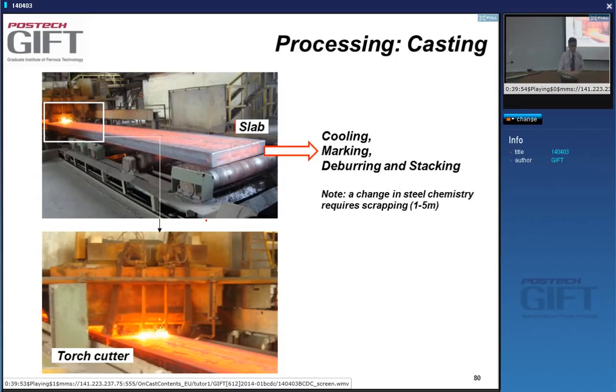Usually for slabs, you're looking at 20 to 25 centimeters of thickness. Their length is about 10 meters, can be longer, 12 meters, but that's a typical length. The width depends on the width of the caster, and it doesn't change very much. The dimension of the caster also defines the maximum width of, for instance, the sheet products that you manufacture. So if you have a caster that can only do 1.2 meters, you will not be able to provide material to customers that need 1.6 meters. For instance, automotive construction needs 1.6, very common, so the caster should be able to provide this material.